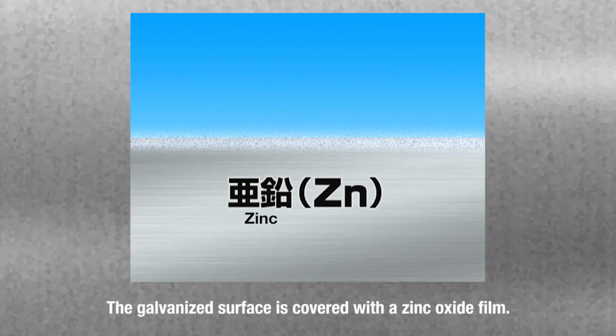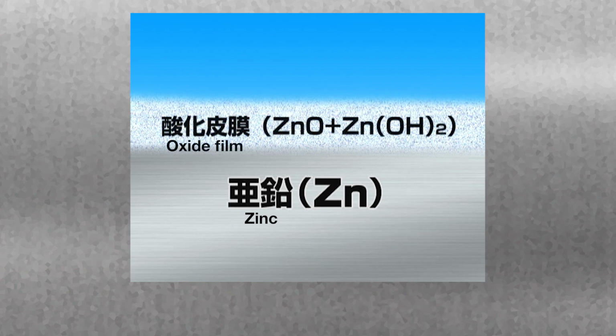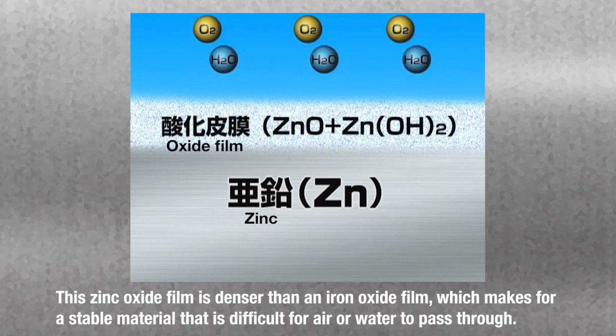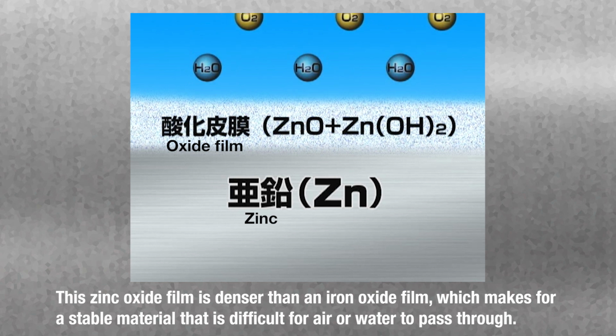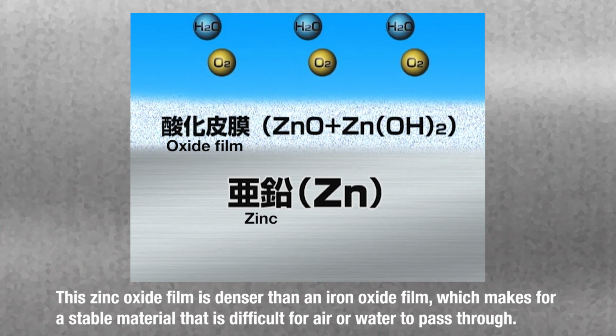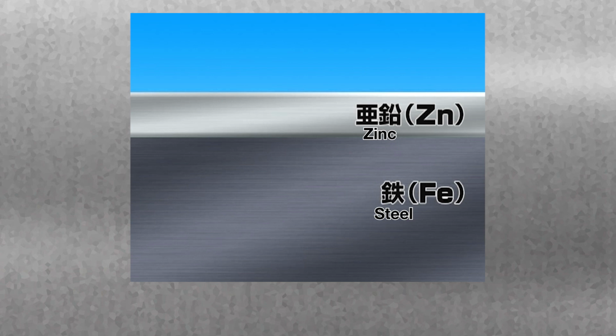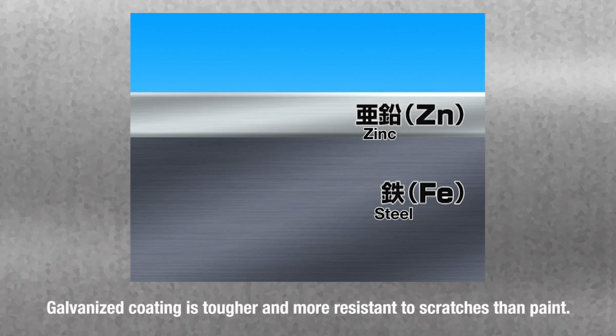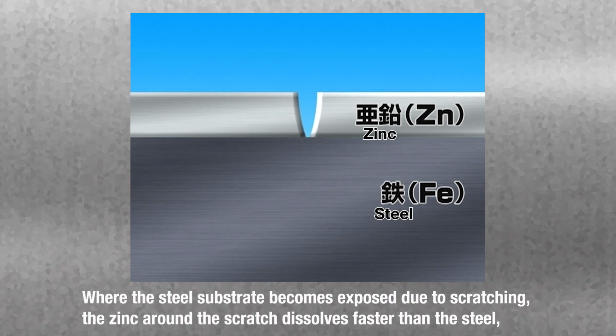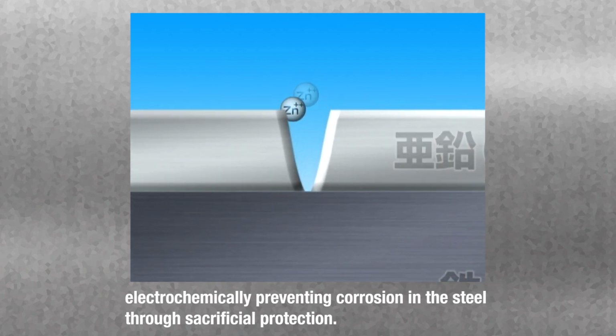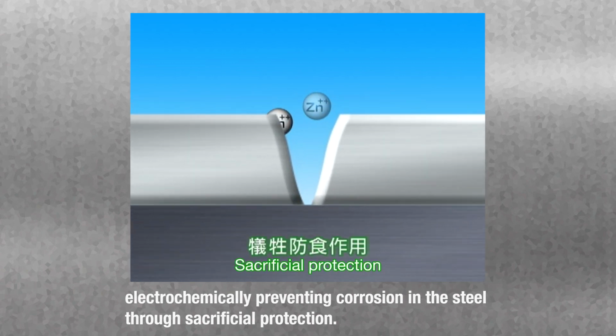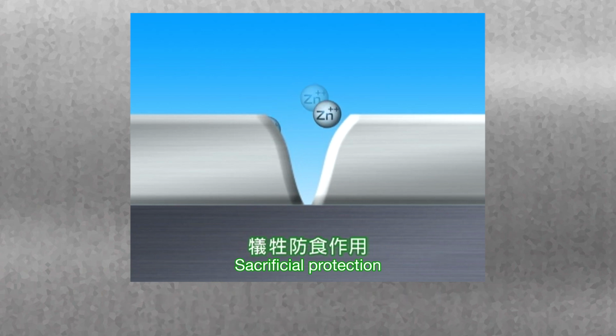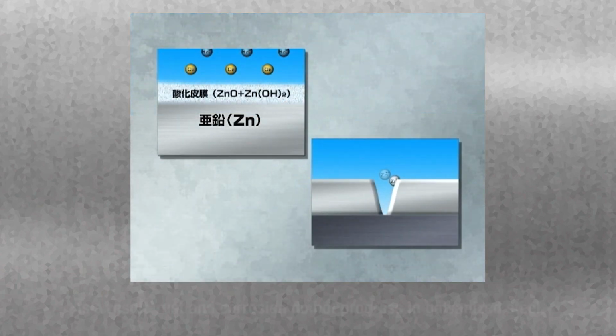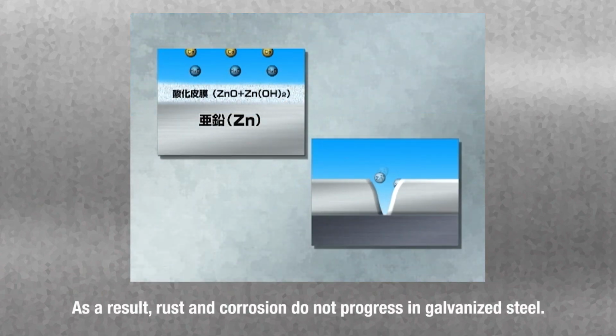The galvanized surface is covered with a zinc oxide film. This zinc oxide film is denser than an iron oxide film, which makes for a stable material that is difficult for air or water to pass through. Galvanized coating is tougher and more resistant to scratches than paint. Where the steel substrate becomes exposed due to scratching, the zinc around the scratch dissolves faster than the steel, electrochemically preventing corrosion in the steel through sacrificial protection. As a result, rust and corrosion do not progress in galvanized steel.